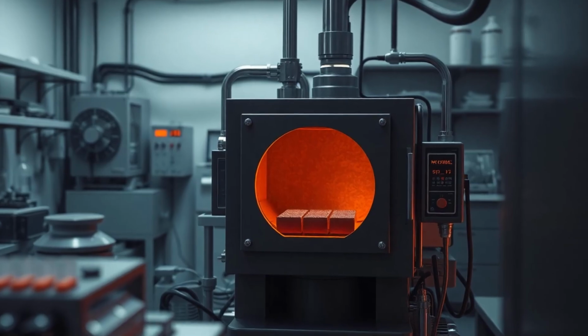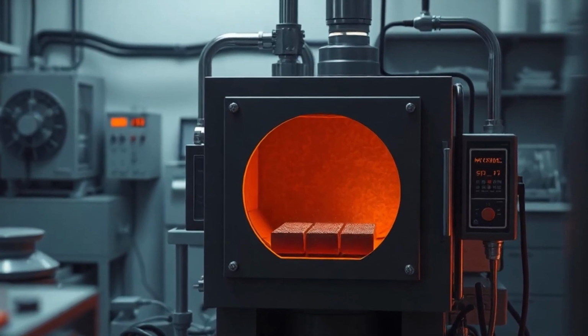Thermal annealing. Think of it like taking the carbon and gently baking it at high temperatures. What this does, in a controlled way, is encourage the carbon atoms to rearrange into more ordered structures, like smoothing out the wrinkles. So they took 2 specific carbons, ACSPC, which was very disordered and had high capacitance, and EL104, a more ordered one. They annealed them at increasing temperatures, and their NMR measurements confirmed it. The Ω values increased, meaning the structure got more ordered.